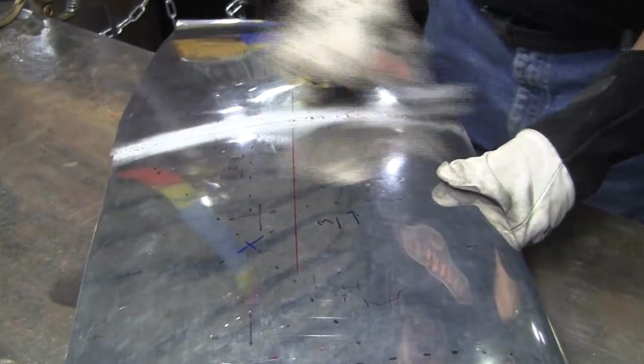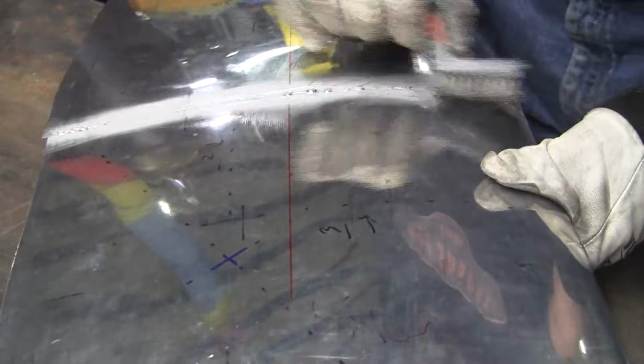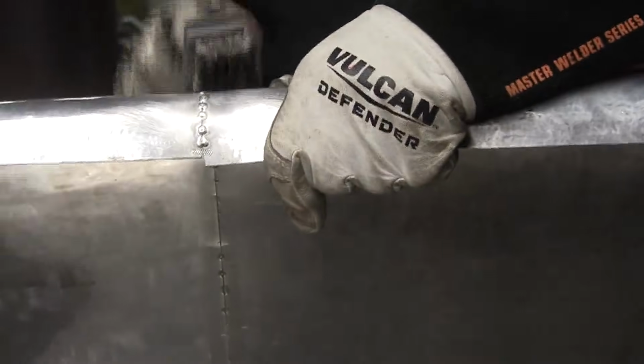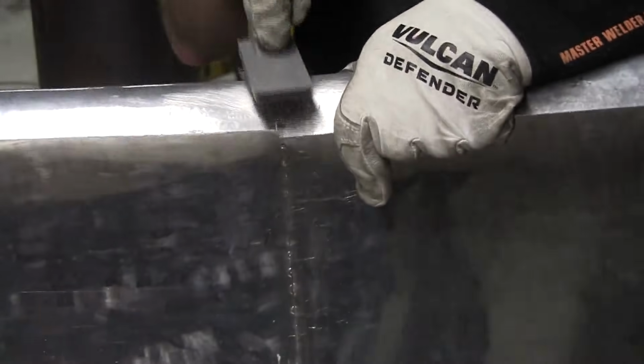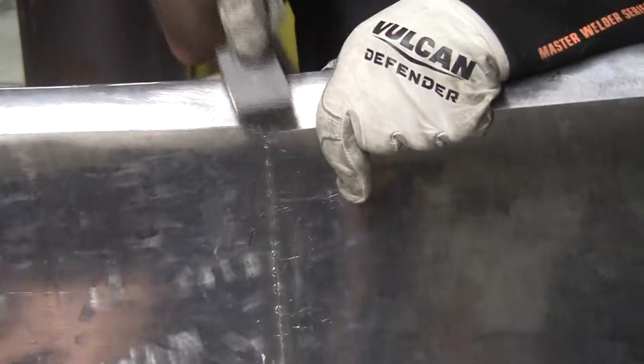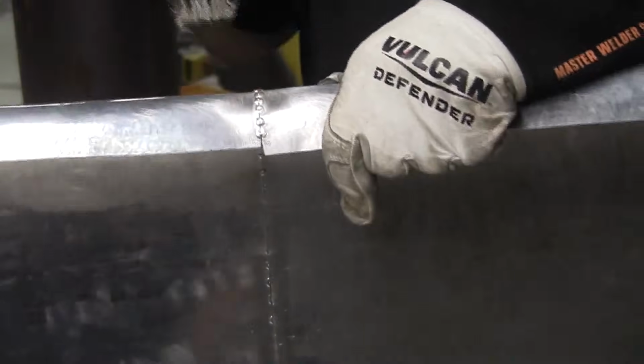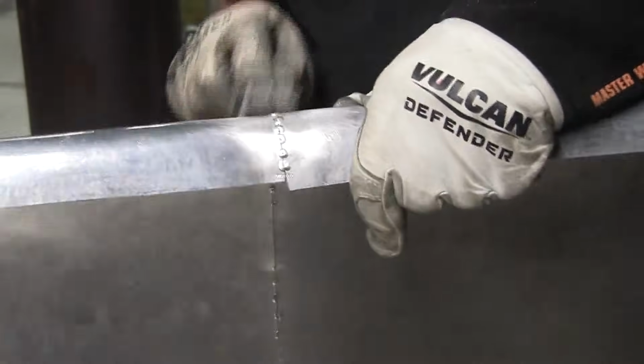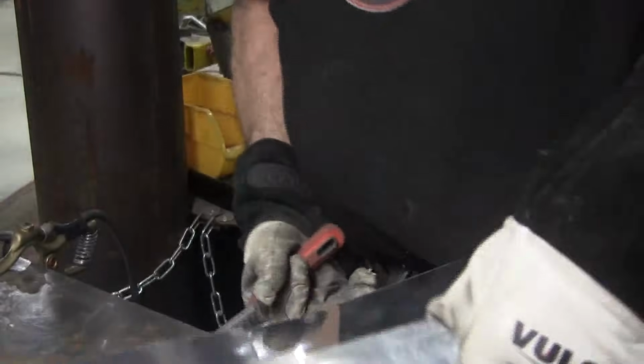Now, TIG welding gets a bad rap for having the potential to crack. And it's my opinion that any cracking in a TIG weld is caused by there not being sufficient heat induced into the area to make what I call the handshake. That's when one side joins with the other. You have to have a certain amount of heat. Now that doesn't necessarily mean your amperage being turned up.